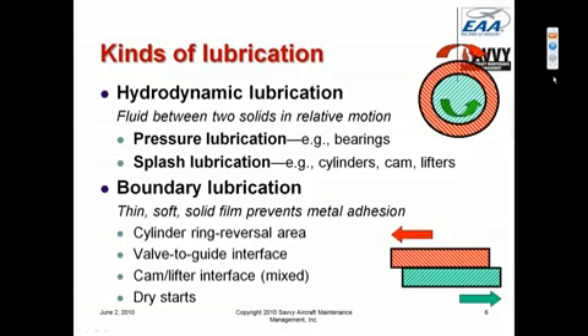And we have two basic kinds of hydrodynamic lubrication that we use in piston aircraft engines. One is called pressure lubrication, where we're actually pumping the lubricant into the boundary between the two moving parts. And the most common example of pressure lubrication is bearings, where there are actually oil galleries and passages that transfer the oil under pressure directly into the bearing between the bearing surfaces, and provide hydrodynamic lubrication. But most of the engine does not have pressure lubrication. For example, the interface between the cam and lifters, the interface between the rings and the cylinder walls, there's no oil under pressure being applied to those surfaces.